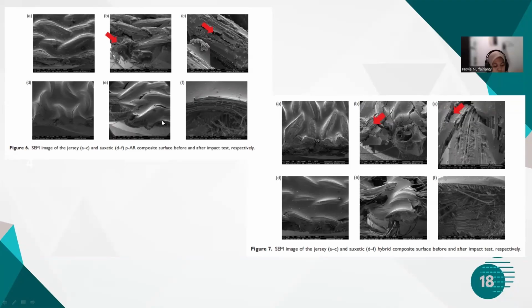This agrees with the graphs presented in figure 3, which show that composites reinforced by auxetic structures present a ductile behavior during the impact test, unlike composites reinforced by jersey fabrics, which present a more brittle behavior, justifying the matrix debonding shown in the same photographs. Therefore, images of the auxetic composites, para-aramid and hybrid, do not show matrix debonding. In this way, the composites reinforced by the auxetic structures also provide better structural integrity of the composite after impact.